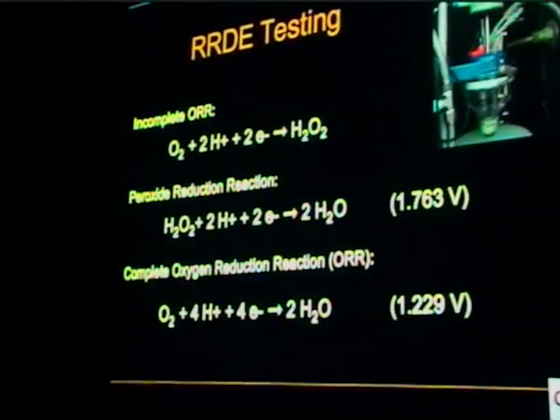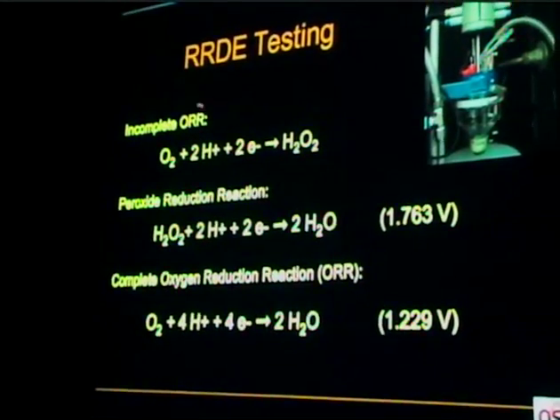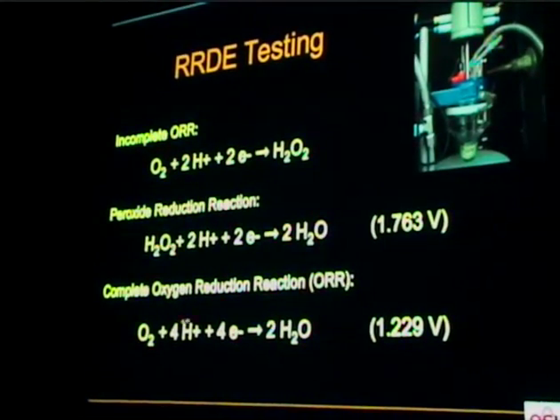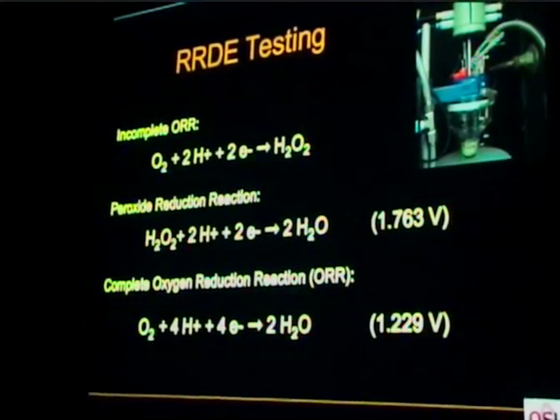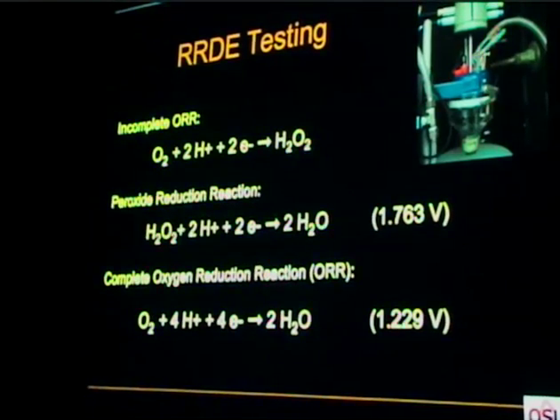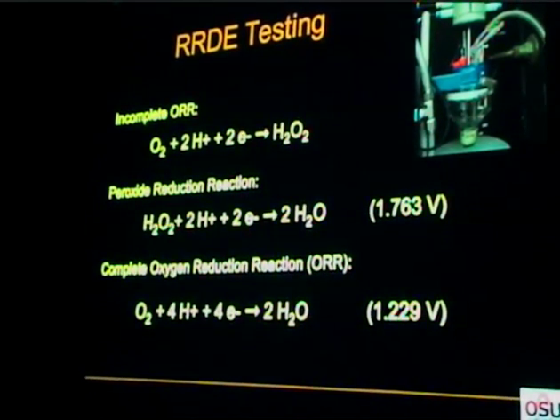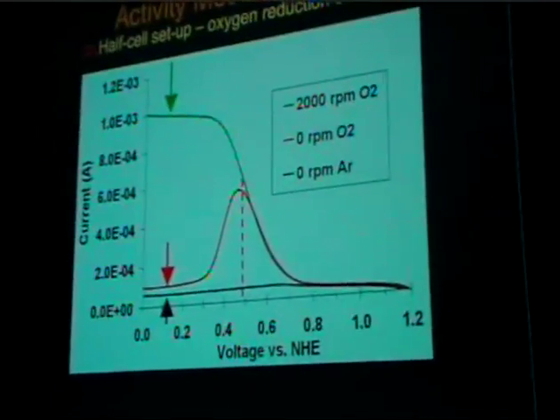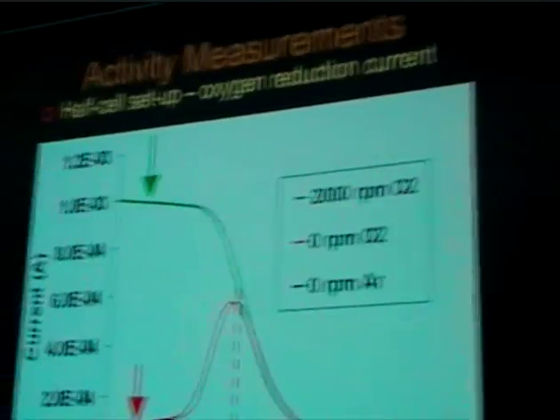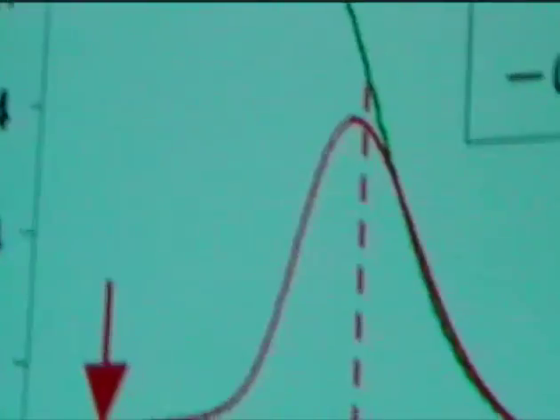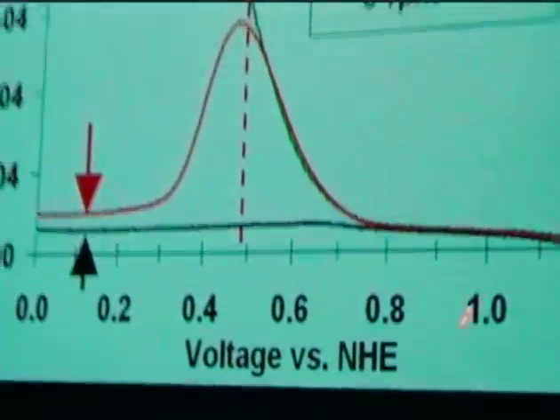So with the rotating ring disc system, we are able to differentiate between these two reactions and get a selectivity value for the four-electron oxygen reduction reaction. Now, this is a typical voltammogram from the half-cell setup that I just showed.